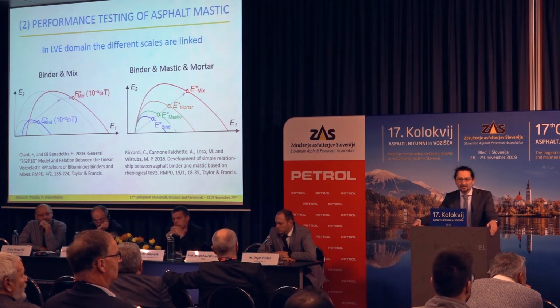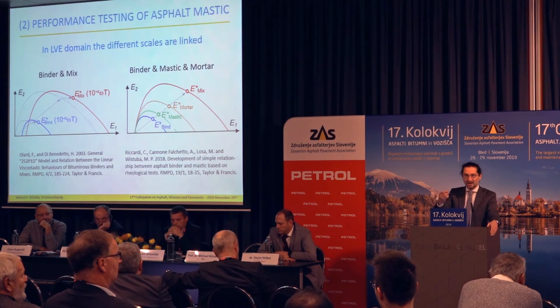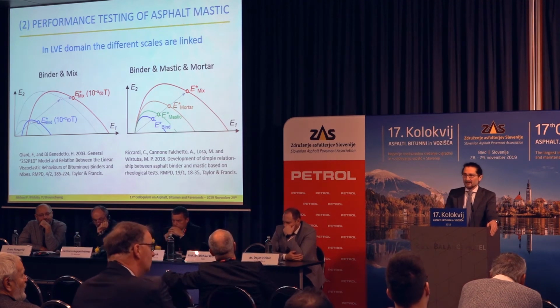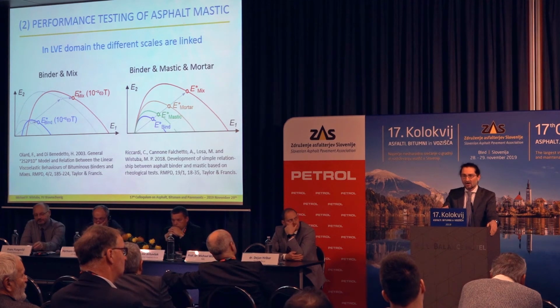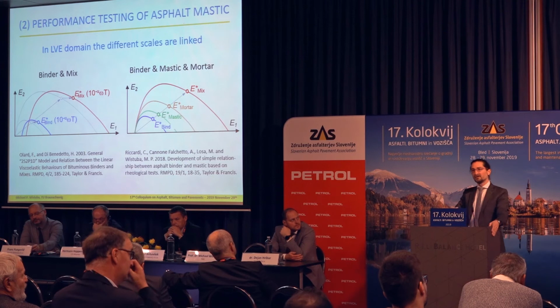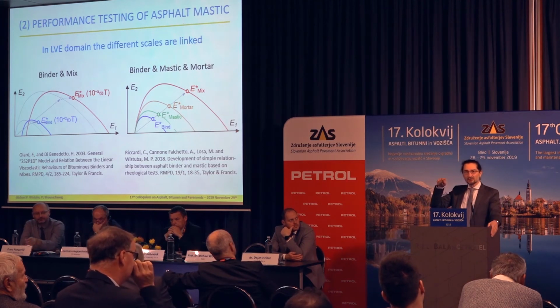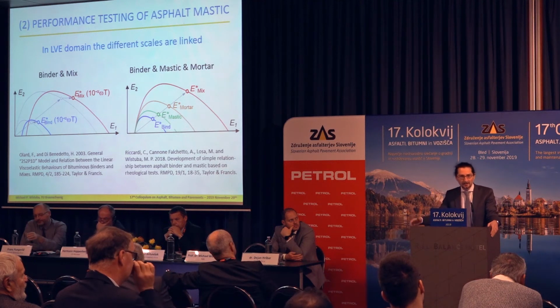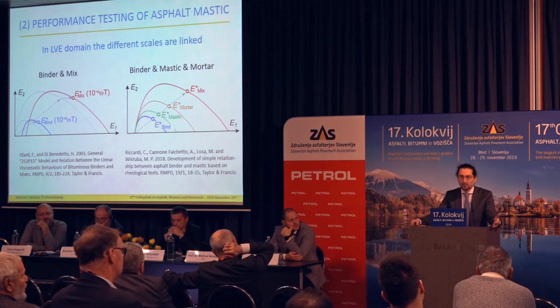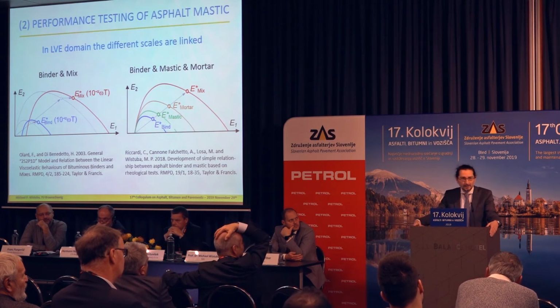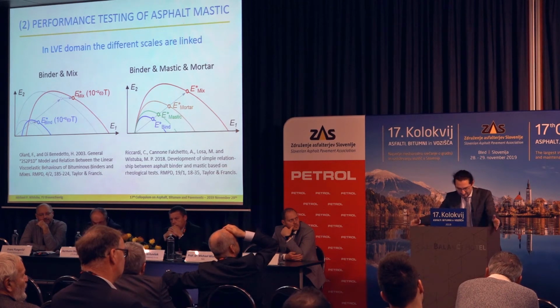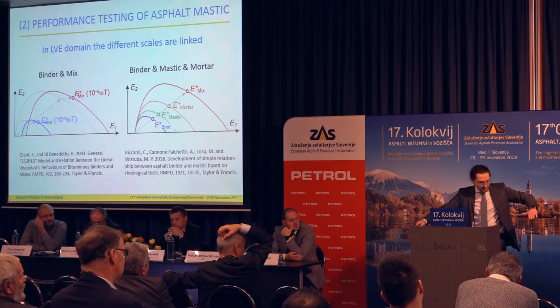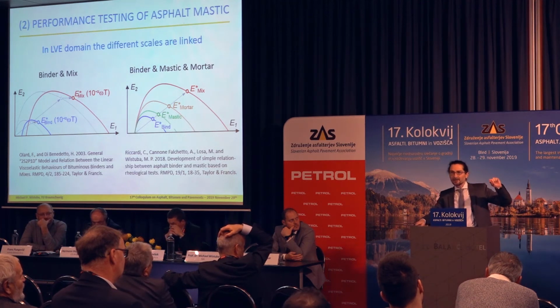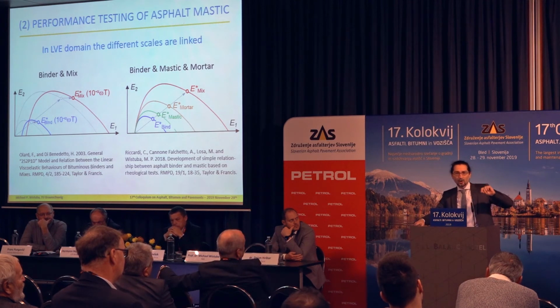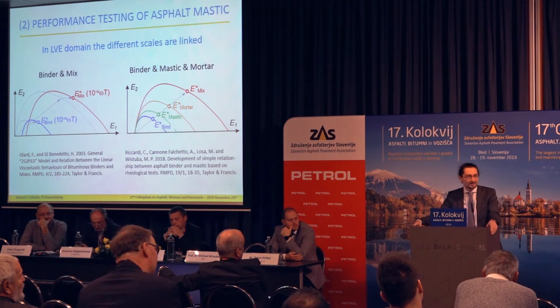But what is the linear viscoelastic domain in practical terms? This is a domain where strain is really small. Let's say for asphalt mixture, you have a strain of maybe 10 to the power of -4. So 10 to the power of -4 means 0.0001 meter per meter in the unit of strain, for instance. So if you have a beam of a thickness of 1 meter, just to give you an example, and you bend this beam, a strain of 10 to the power of -4 means 0.1 millimeter. So it's a very small strain.